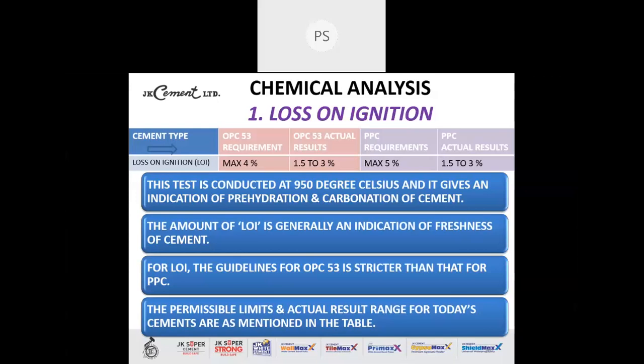Now this test is conducted at 950 degrees Celsius, and it gives an indication of prehydration and carbonation of cement. Second point, the amount of LOI is generally an indication of the freshness of cement. Fresher the cement, lesser will be the LOI, and vice versa.